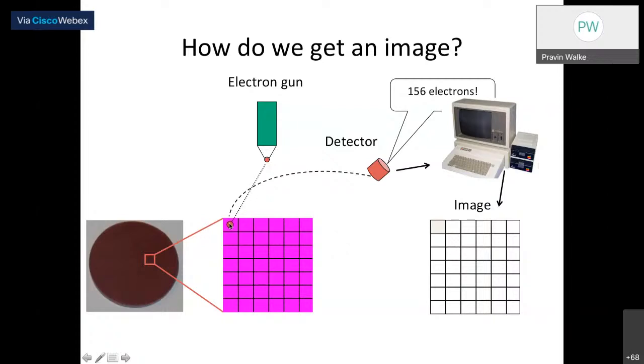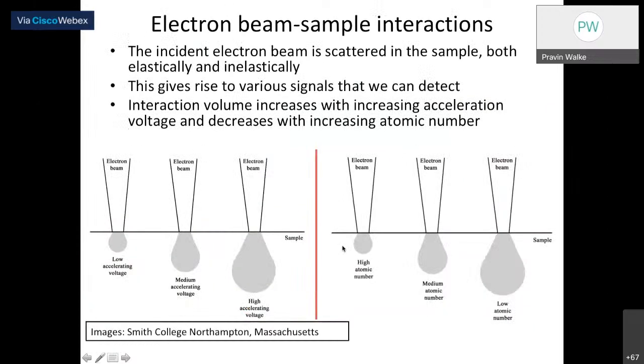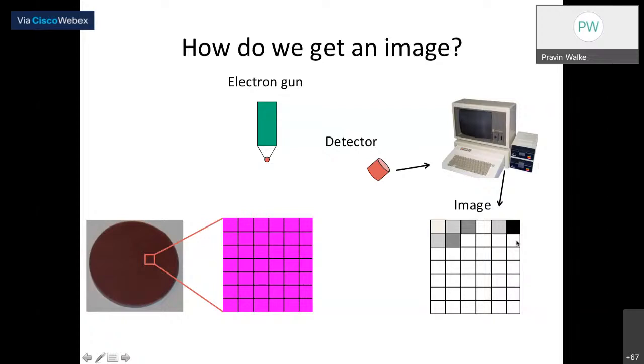If you move further towards another pixel, a similar action happens on that spot, and you find that more electrons are generated, and you can see how the shade has changed. The color contrast changes just by changing the number of electrons received by the detector. We scan the complete specimen with the beam, and convert all of that into the given region. Here you see the number of electrons changing, and the shades correspond to the number of electrons generated and detected. This is how the whole scan happens over this region, and we convert it into the picture form. This color contrast generates the image.